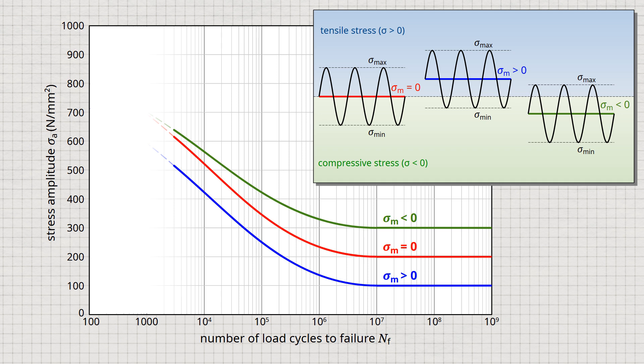The reason for the increased fatigue resistance at compressive mean stresses is due to the fracture mechanism. Fatigue fracture is usually caused by microcracks in the sample surface. These microcracks tear open more and more when subjected to tensile stress, and the crack spreads deeper into the material with each load cycle. With a compressive load, on the other hand, the cracks tend to close and crack formation is made more difficult. We will go into more detail about the fracture mechanism under dynamic loading later in this video.